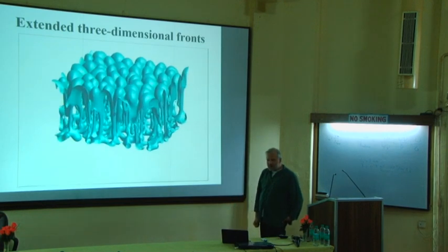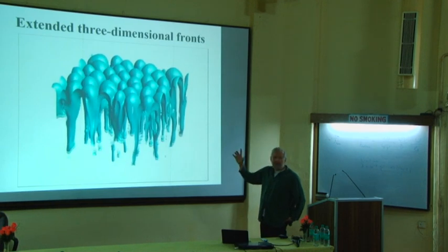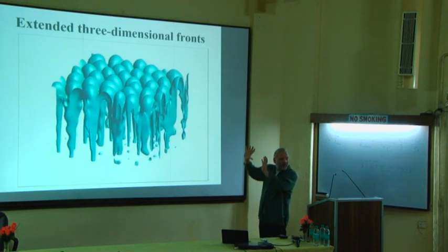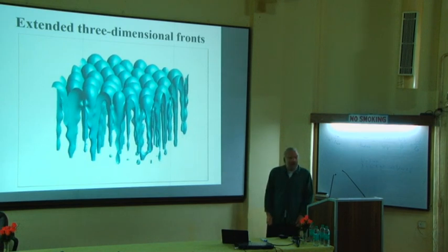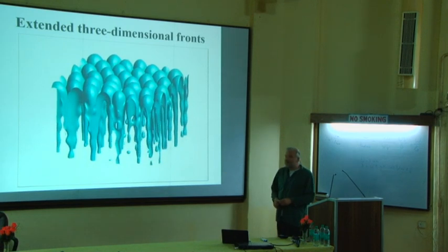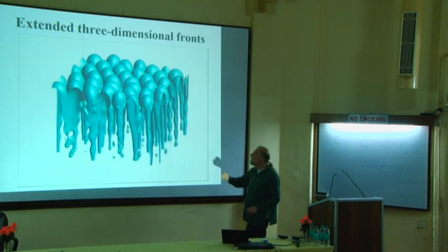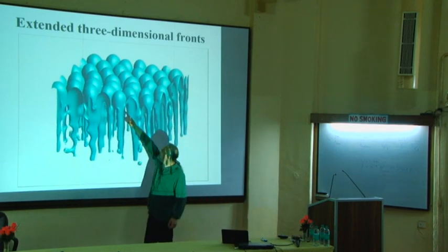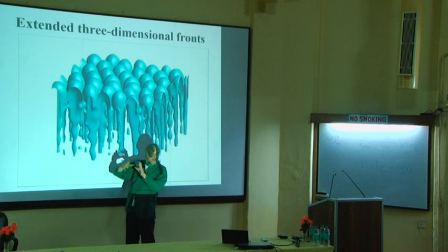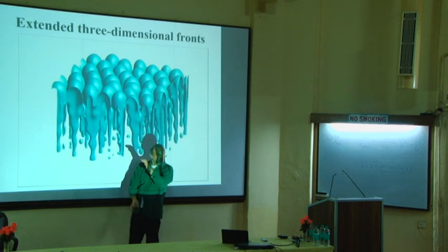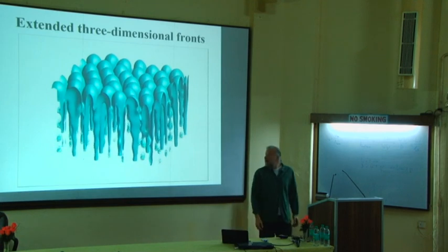So this grows upward, and with my virtual camera, I follow the front. So you see that you can study phenomena of considerable complexity. There are solid cells, you have grooves in between, and then in between three cells, you have a liquid channel that forms. You have pinch-off events and all that. And so this can quantitatively describe solidification cells.